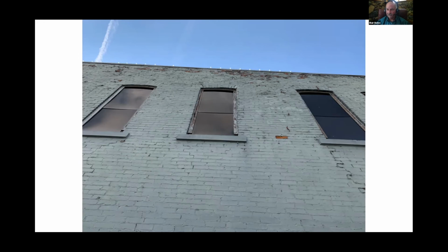Even when we water blast, we put a standoff tip. So we'll go ahead and put a stripper on, and then if we have to water blast it off, we stay a certain distance away from the building. And the typical guy on our crew is leaning into it to get it a little better because he couldn't get it off. So we put a rod next to the power washer rod, so you can't get any closer than 20 inches or 28 inches, depending on the sampling that we've done, so that we know we're not eroding the face off. When they do their sample, look on the ground. Are we seeing chunks of brick or the orange powder from the brick or the mortar, or are we just seeing the nitrogen and the paint? If you're seeing anything other than the paint, then they're eroding the brick face at the same time.